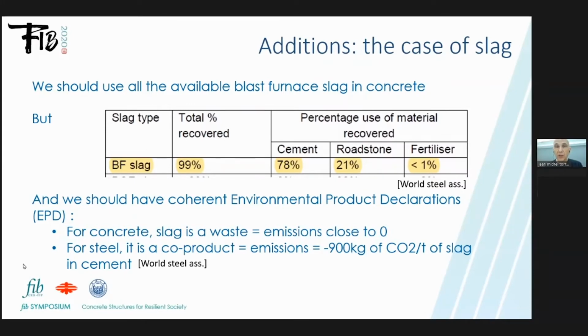It means that the emissions are close to zero. And for steel, it's a co-product, and they deduce, in fact, in the CO2 emission of steel, they deduce 900 kilograms of CO2 per ton of slag, which is used in cement, and that is the main part of the slag.